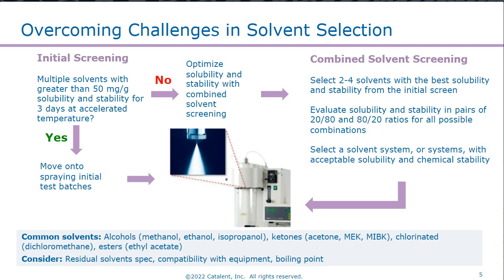Key considerations in the solvent selection are thinking about the residual solvent spec that we're going to need to meet for the finished product, which of course is related to the toxicity, the tolerability of the solvent. We also need to consider the compatibility of the solvent with the spray drying equipment. So some of the more aggressive solvents that we may look at to dissolve the API may also be very good at dissolving some of the seals that we have in the spray drying equipment. And of course, the boiling point of the solvent will also be important when we're establishing the spray drying conditions that we're going to be using.